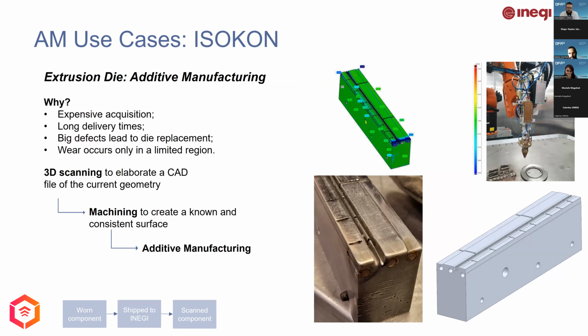The extrusion die appears to be suitable for repair with additive technology for several reasons. It is an expensive component with long delivery times. Big defects are difficult to repair and normally lead to die replacement. Also, the main wear occurs only on a limited area of the part. The proposed steps for the repair through additive manufacturing are to perform a 3D scan of the part to assess where material needs to be added for a successful repair, machining to create flat and consistent surfaces, and to enable us to reach the deposition area on all areas of intervention. And finally, the additive manufacturing process can be done. The process in here is direct energy deposition using powders.